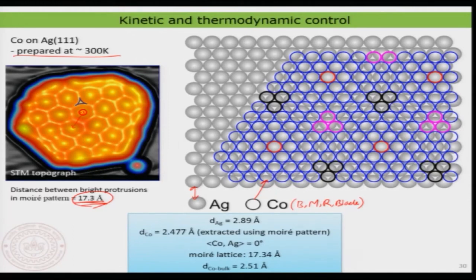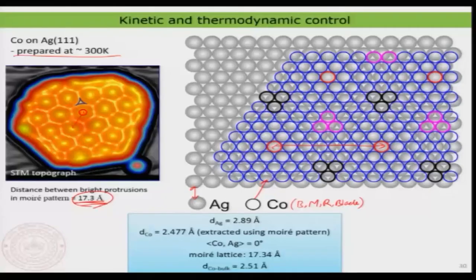Now what I did is, looking at the bulk super lattice parameter, which is basically the distance between these two points, the atom of the adlayer is actually on top of a silver atom. So you can see now, if you move along this lattice, the atoms are basically changing their position, and only after about 1, 2, 3, 4, 5, 6, 7 surface atoms, it is basically some kind of a 7 by 7 superstructure. Now this distance is something I obtained from the Moiré lattice.